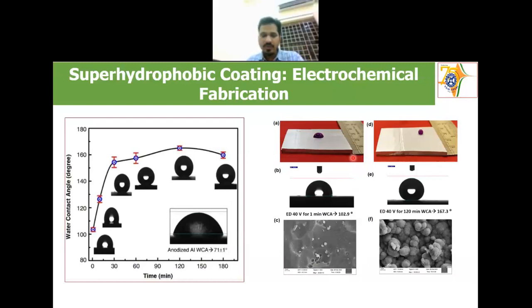There are reports already using cerium stearate based coatings. So we want to study at what potential and how long you should do the deposition to get the maximum coverage. And we want to know fundamentally, because we are adding cerium 3 plus, which is a corrosion inhibitor for aluminum, what is the synergy between the superhydrophobicity and the cerium 3 plus, the active corrosion protection, and how good it is. So these are the photographic images you can see here.